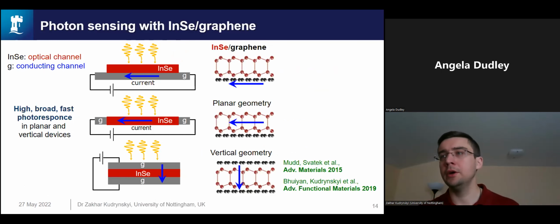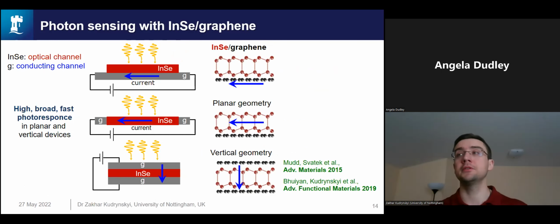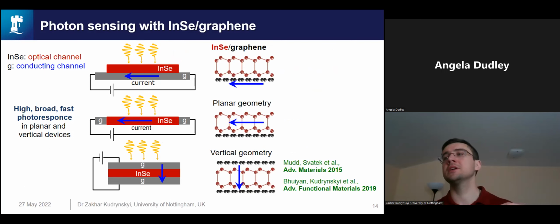So now we can learn from this study and try to make photodetectors based on this effective charge transfer and based on good electrical and optical properties of the layer. So we can use different types of geometry. In this device that I have shown you, indium selenide was an optically active optical channel, and graphene was a conductive channel. But here we have also studied other structures where indium selenide acts both as optical and conducting channel, and graphene serves as transparent electrodes. Graphene makes an ideal electrical contact to 2D indium selenide, better than any metal.